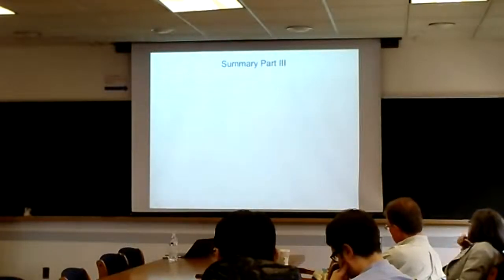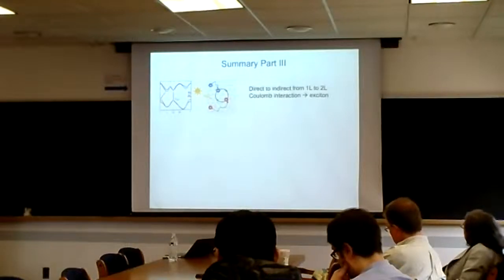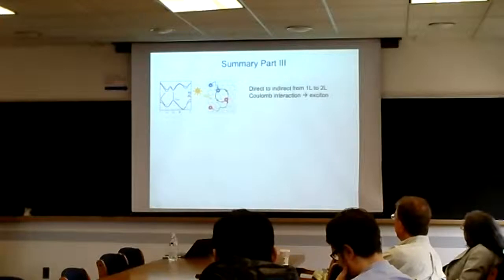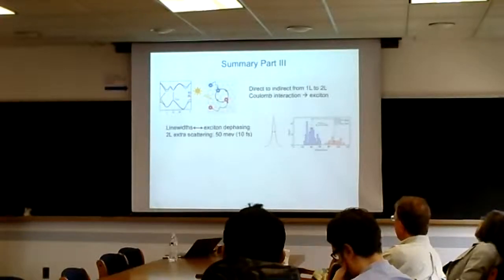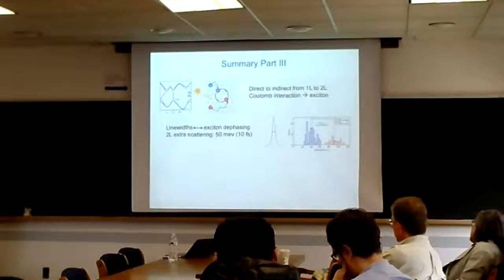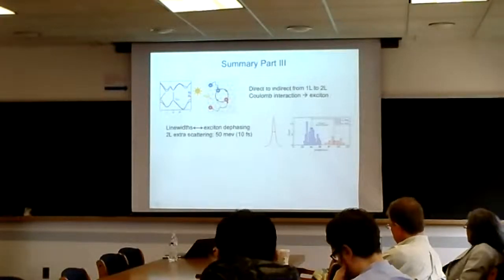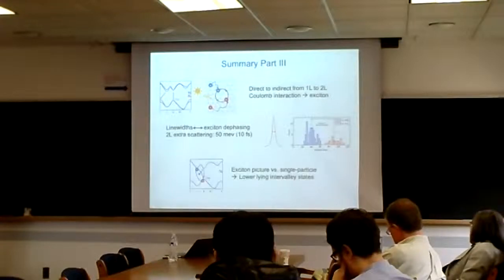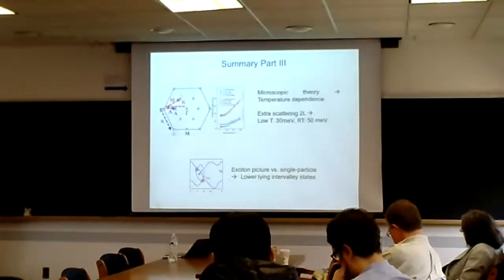So with that, I just want to summarize because my time is almost done. When you go from direct to indirect gap material, from the monolayer to bilayer, you still have to consider the Coulomb interaction for scattering processes. Because of that, you're adding this extra line width of 50 meV in the bilayer materials, which would not be the case without the renormalized interaction for the excitons. The single particle picture would not give us the direct correlation to the experimental results from theory. And at the end, there are new lower-lying intervalley states due to the screening effect.